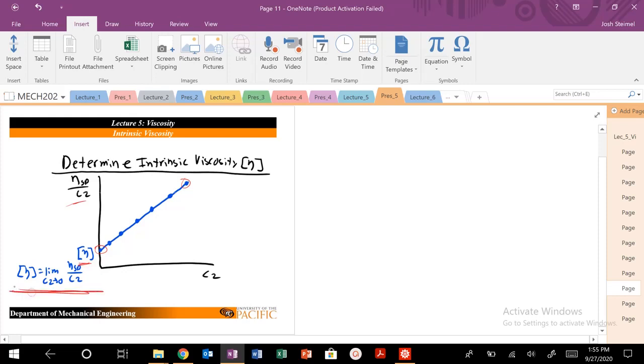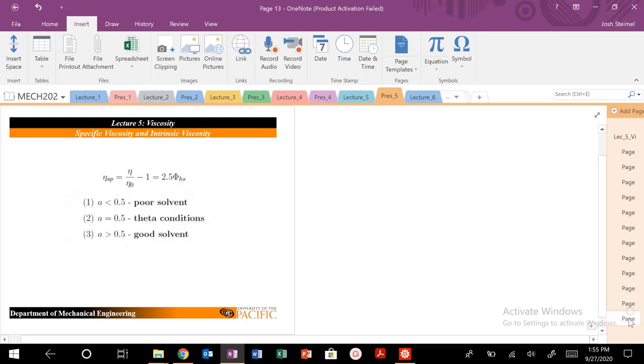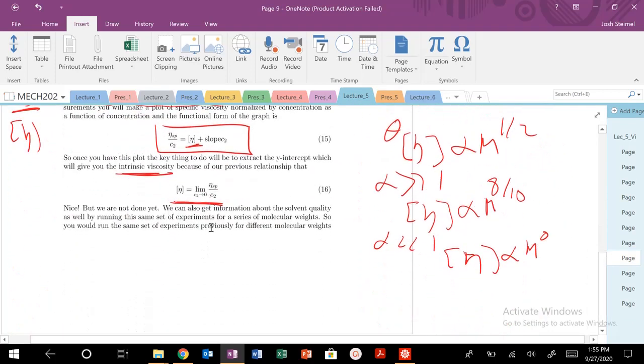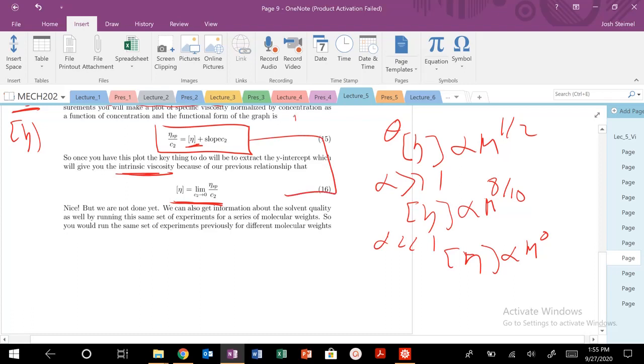Look at the definition: our intrinsic viscosity is just the specific viscosity over concentration as the concentration goes to zero. So as concentration decreases toward zero, we approach our limit and get our intrinsic viscosity. We can basically call it at that, and we're good to go — but not quite, because we could do a little bit more. If we run a series of experiments at a single molecular weight, we can also run the same set of experiments for a series of molecular weights to get information about solvent quality.